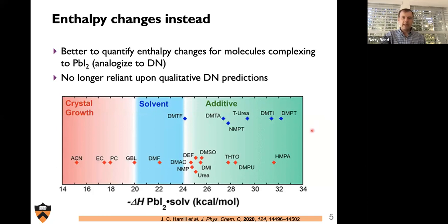And we see that, again, we have these lowly coordinating solvents which lead to crystal growth, intermediate ones that are good for principal or primary solvents, and then ones that ought to be used sparingly because they coordinate very strongly and it might be very challenging to remove these. And note that DMSO exists somewhere on the edge of this solvent to additive regime, but clearly ought to normally be used in the context of an additive and not a primary solvent.